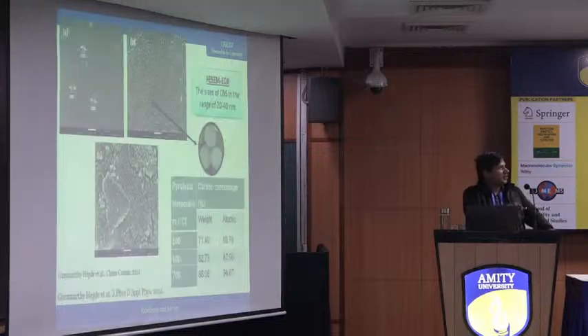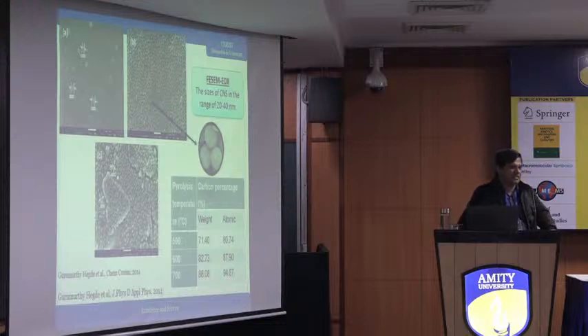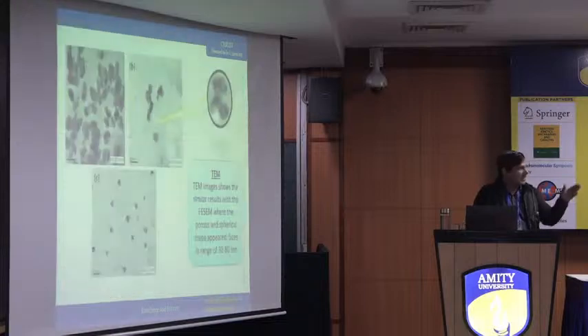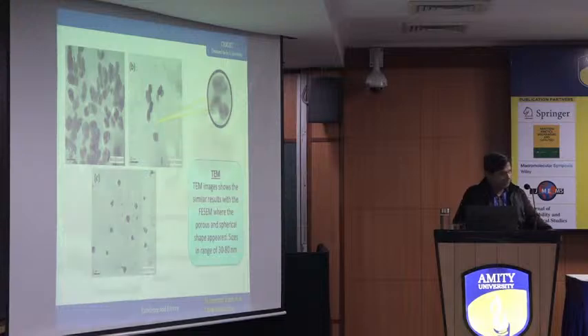Next we subjected it to FESEM. You can see we took a very small portion from here. You can see all the sizes of these porous nanoparticles are the same. Very uniform sized nanoparticles are formed. And you can see the carbon percentage increases from 500 to 600 where it is 80%, then at 700 it is 94%. TEM again says that they are not only spherical, they are also porous in structure.